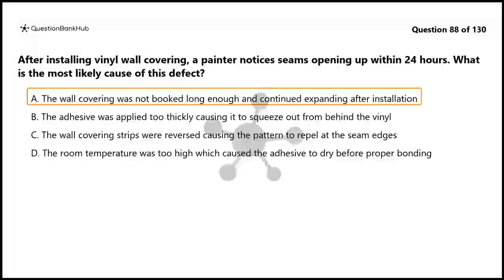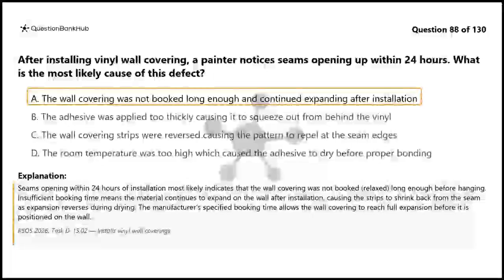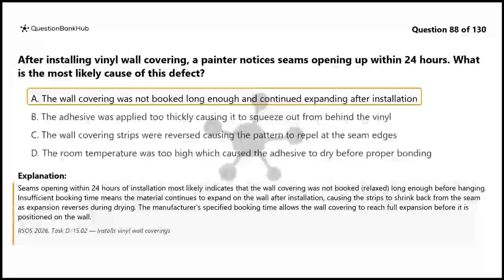The correct answer is A. Seams opening within 24 hours of installation most likely indicates that the wall covering was not booked, relaxed, long enough before hanging. Insufficient booking time means the material continues to expand on the wall after installation, causing the strips to shrink back from the seam as expansion reverses during drying. The manufacturer's specified booking time allows the wall covering to reach full expansion before it is positioned on the wall.